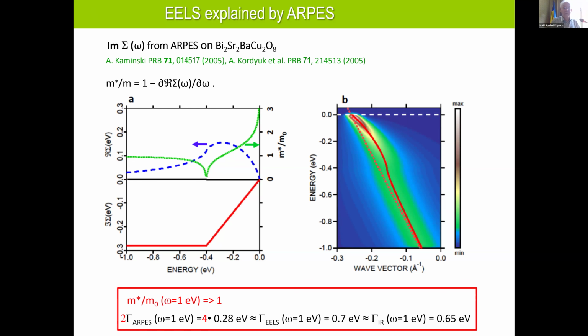When you calculate the spectral function as a function of momentum, then you have a renormalization of the band at low energy compared to the bare particle band, which is shown here as a dashed line. But when you go above this saturation point at 0.4 eV, the renormalized dispersion goes back and approaches again at high energy the bare particle band structure. This means you have again the effective mass of 1. So at high energy you have nearly free electron behavior, but at low energy you have this renormalization.